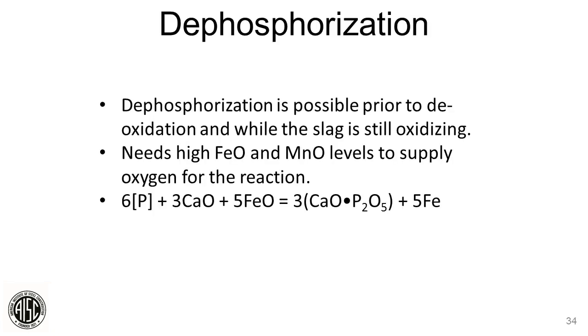So dephosphorization, again, a key part of the electric arc furnace process. It needs to dephosphorize the steel to get it out. To make that happen, we have to have very high FeO and MnO levels in the slag to provide the oxygen for the reaction. And basically, a little chemistry there: the lime, CaO, grabs the phosphorus oxide, absorbs it in the slag, and removes it from the steel. Next slide.